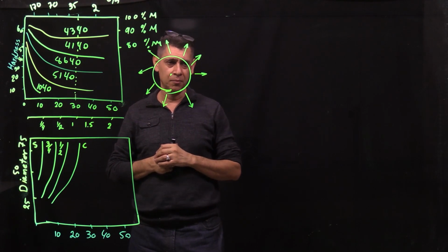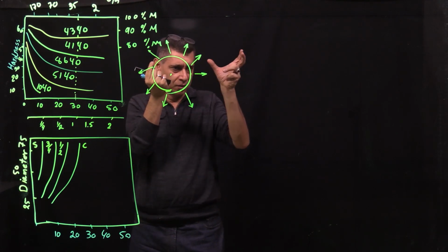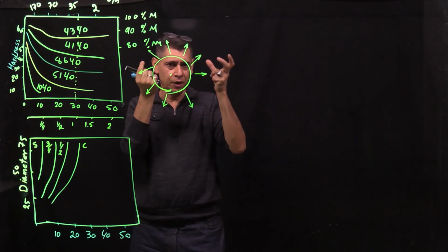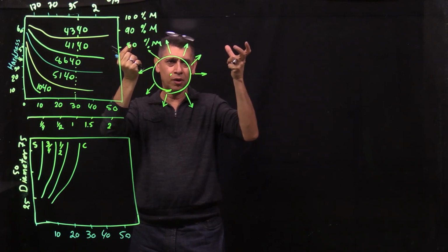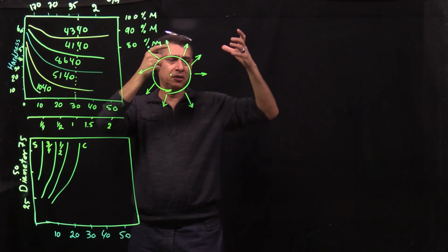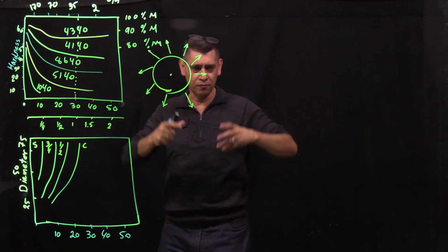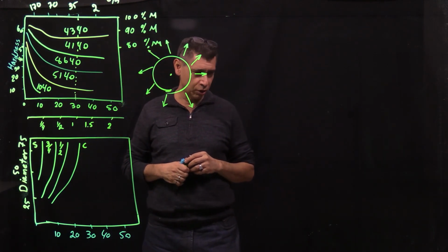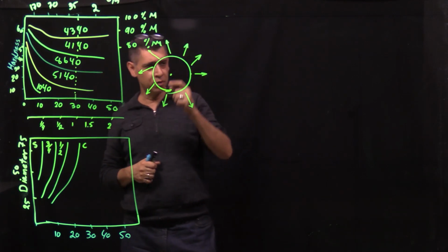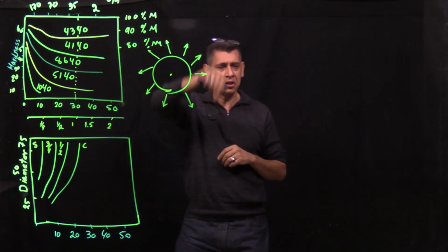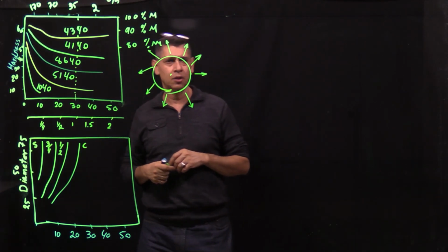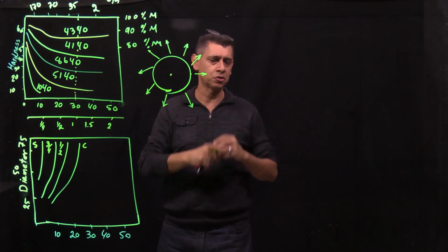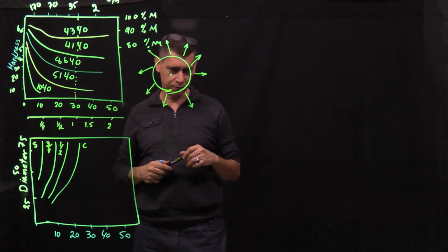That's correct. But if you have a needle and a 6-inch bar, the thermal capacity of these two are not the same. So definitely it takes longer for a 6-inch round bar to be cooled down. That's one. And more importantly, the center of the needle is going to be instantaneously quenched, but the center of a 6-inch bar takes longer.